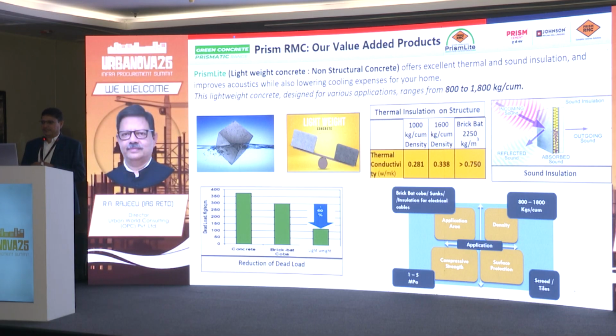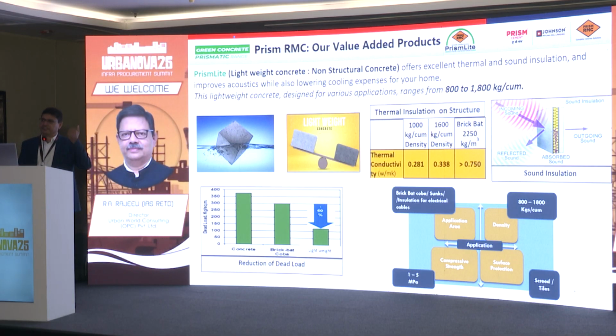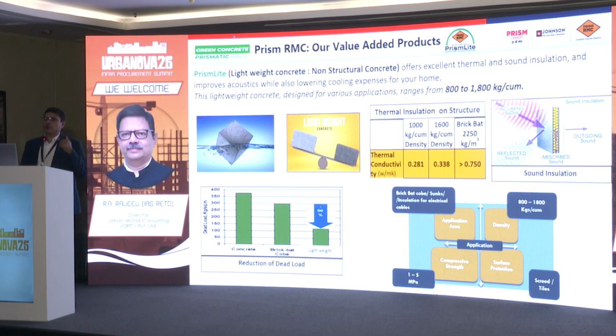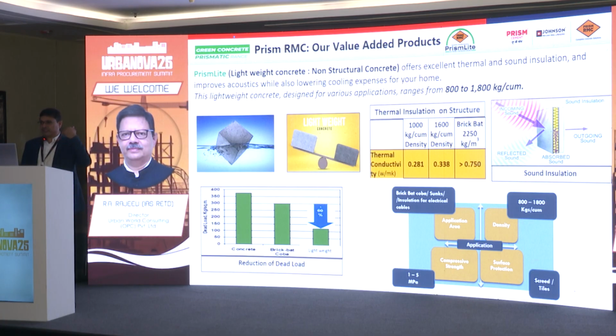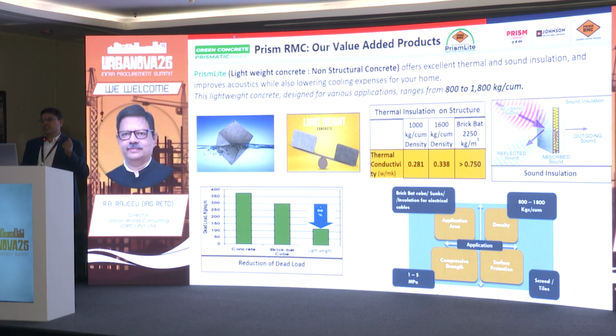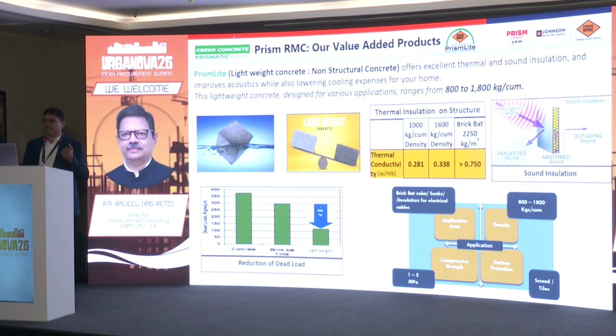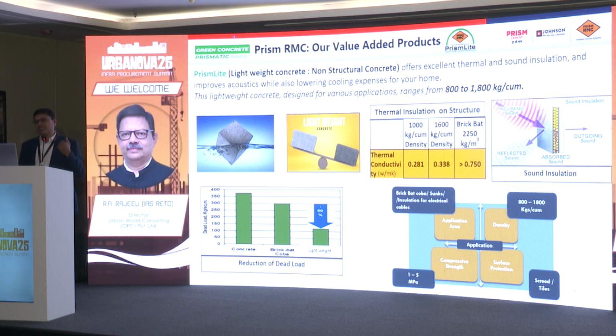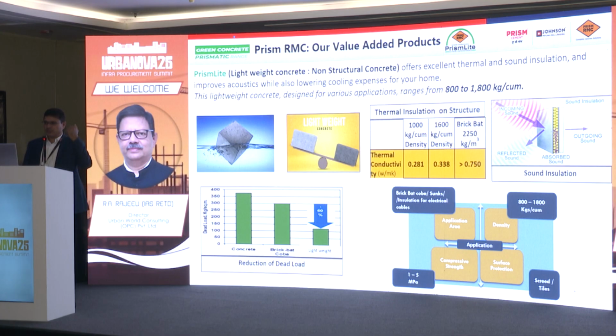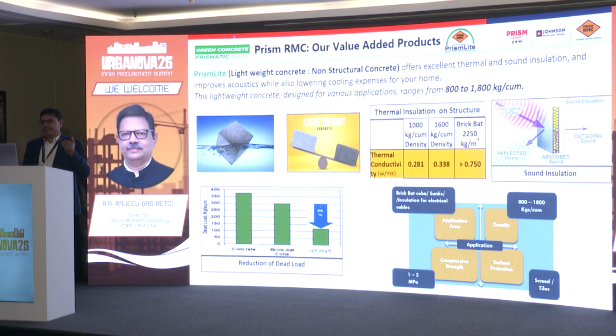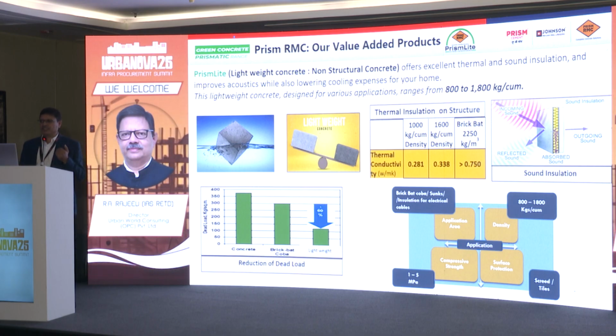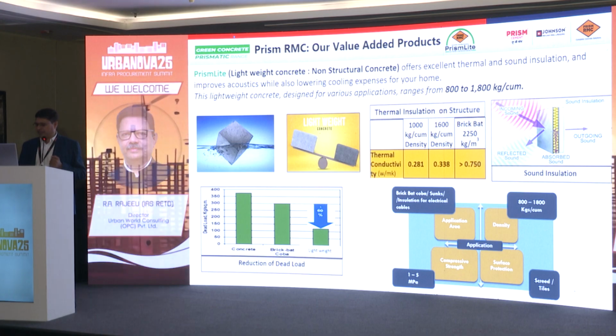screed concrete. Secondly, we have structural lightweight concrete as well, where some structures require strength along with lower density. There we use sintered fly ash aggregates, and we are able to achieve concrete from M20 up to M35, with density from 1500 to 1800 kg per meter cube. That is also available for lightweight concrete.